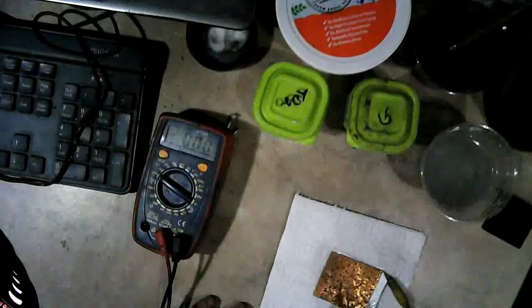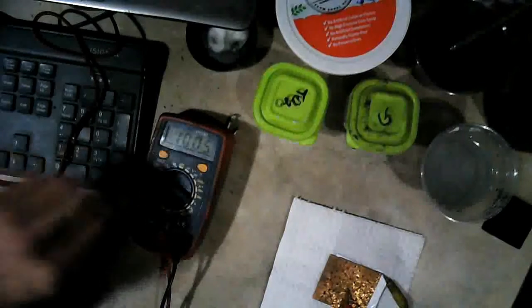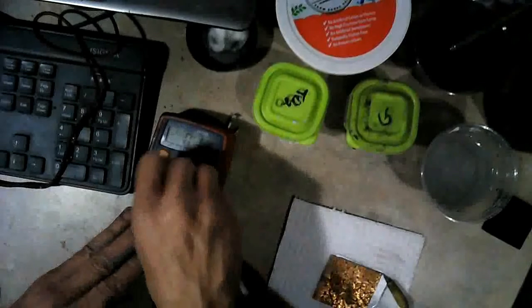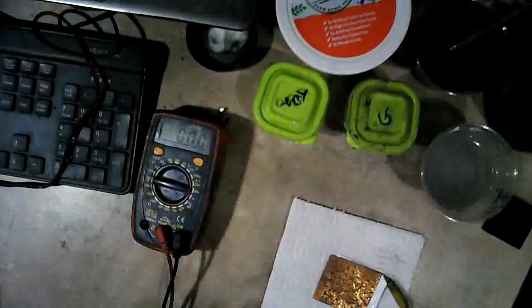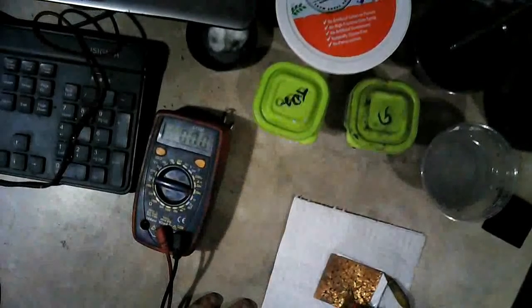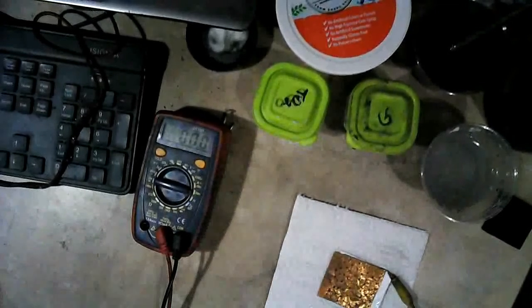It's been less than a minute and we're almost back all the way up. That's a nice self-charge. I'll give it a little extra time. I'll be back in a couple minutes. Well, it didn't have to wait long. It just went a little bit higher and then kind of stopped. We're going to measure it right there at 1.005. A little bit of a voltage decrease, but we were expecting that. That's the pattern - the voltage slowly decreases and the amps go up. Let's see what our amps are now. Three, two, one - 21 something, maybe 21.0.